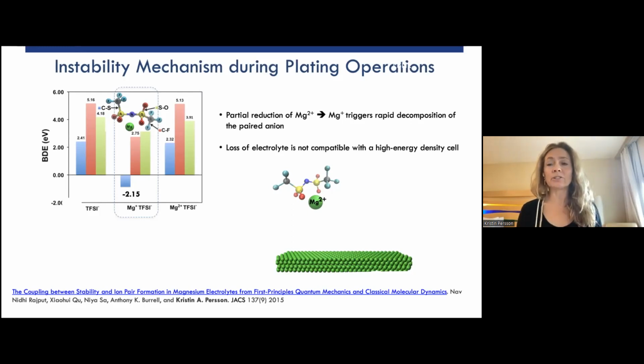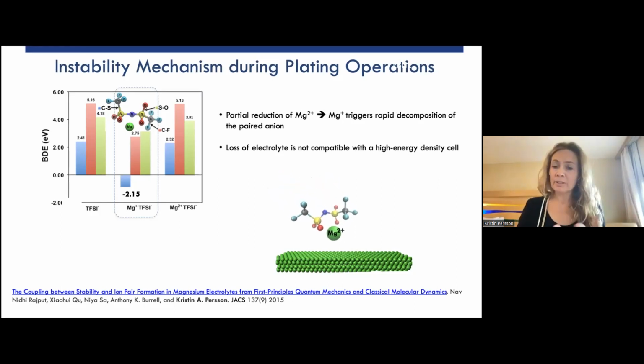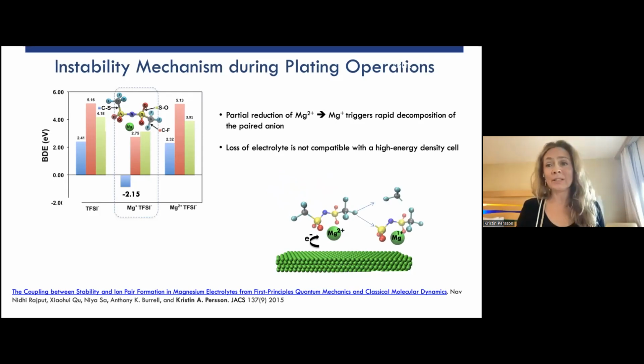And this is really a signature of the fact that magnesium 1+ is highly reactive. It hates being in that state. So what happens is that the TFSI will sacrifice itself and literally take up the electron and break. So if I were to have a little cartoon of this, here comes a delivery vehicle with the contact ion pair, takes up 1 electron. This is a very, very short intermittent state, so short that we have not been able to measure it. We've had people look at it, but it's very short. But what we do see in both experiments and in computations is that TFSI breaks during plating conditions.